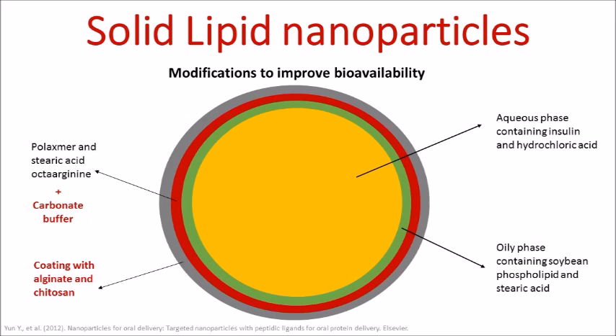The main composition also reduces the trypsin degradation so that the remaining insulin is 25.7% at 4 hours, but it is subjected to partial degradation due to the harsh environment of the GIT. Thus, we can add chitosan and alginate coatings to protect the formulations. These are some suggestions for modifications of solid lipid nanoparticles modified by stearic acid octaarginine to reduce their degradation and to improve their